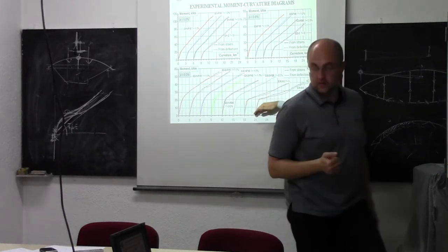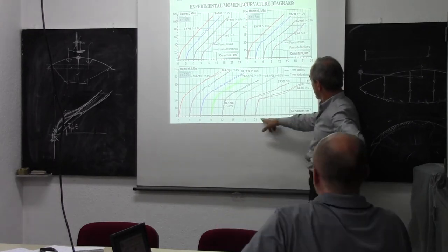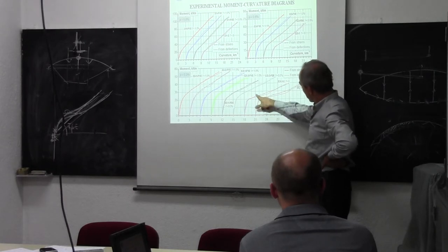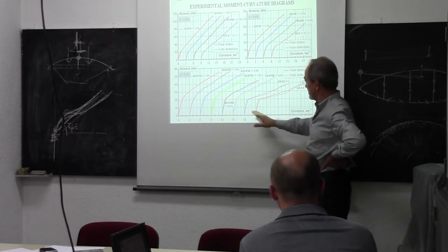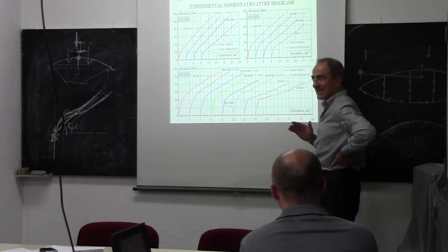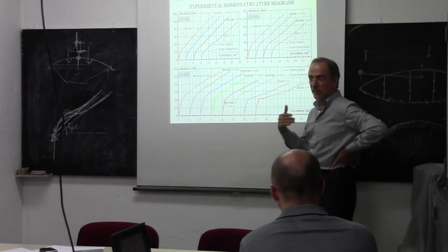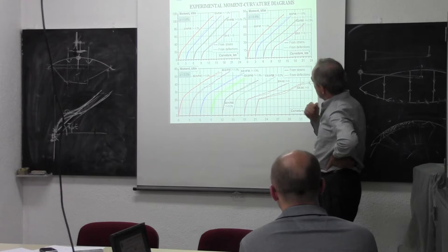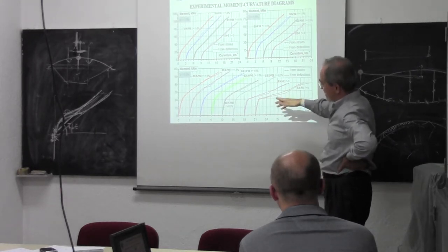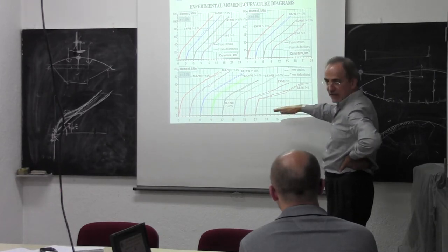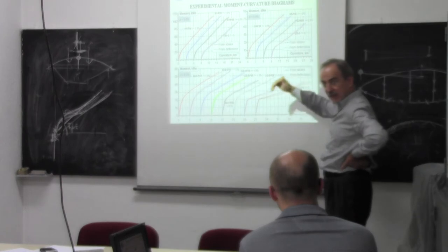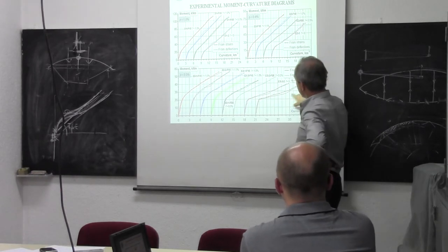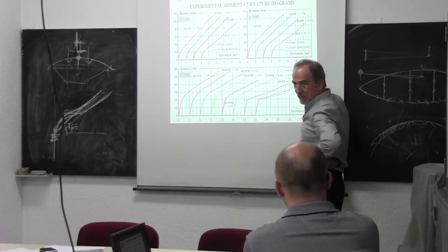The same idea. But here the horizontal axis is a little bit confusing, because for this diagram zero is here. But this is the idea: when you have less reinforcement, you have a bigger tension stiffening effect. And according to these results, you have exactly the same when you have the same quantity of reinforcement and increase the fibers in the concrete.